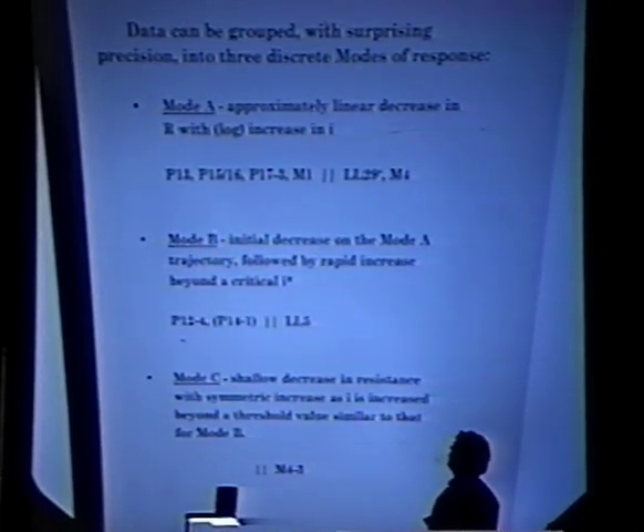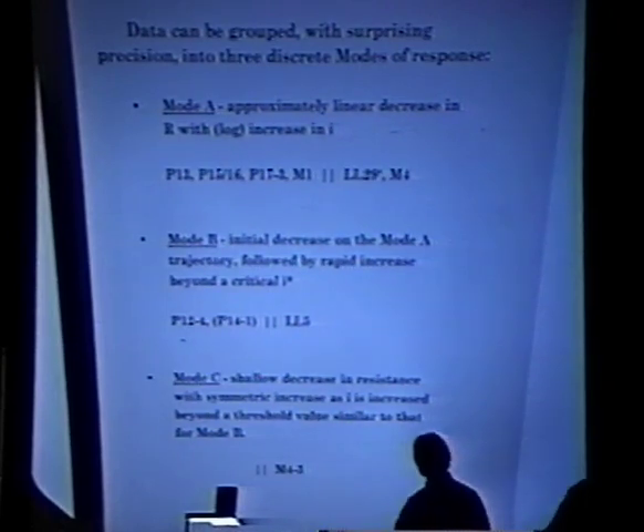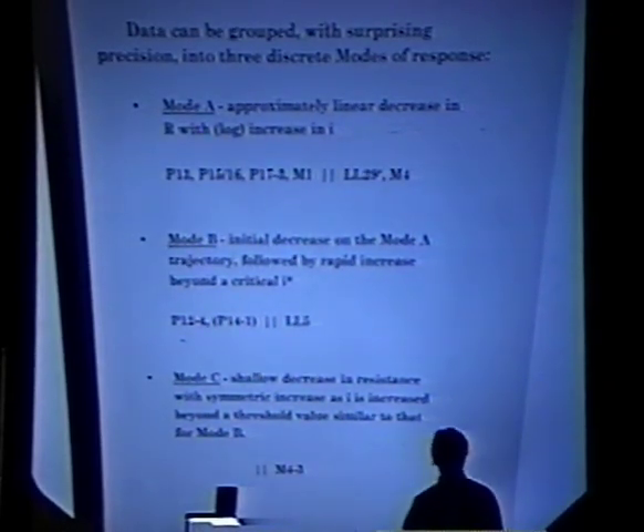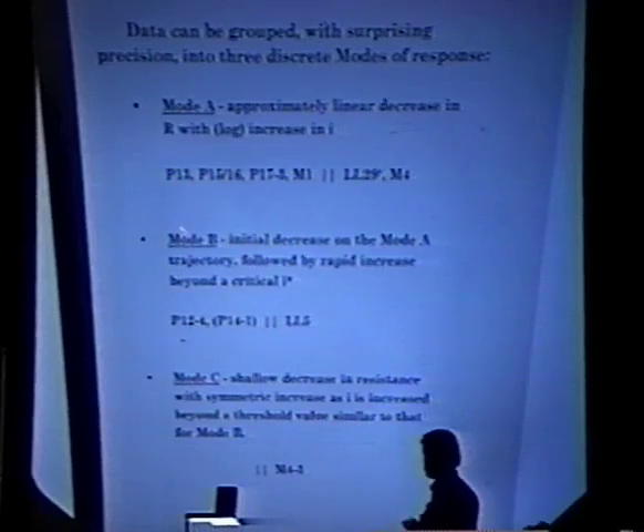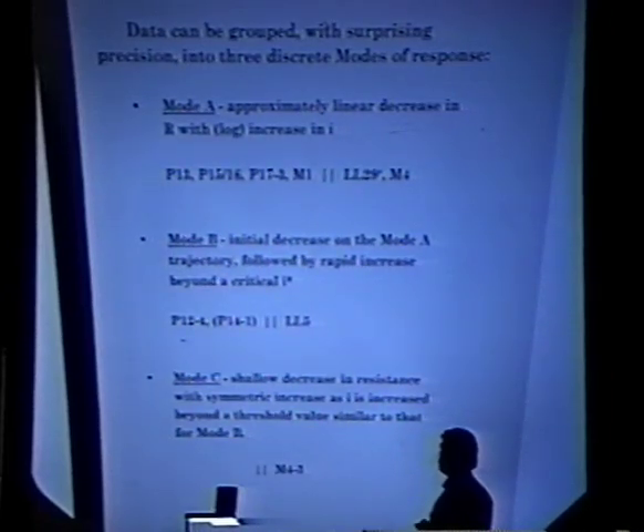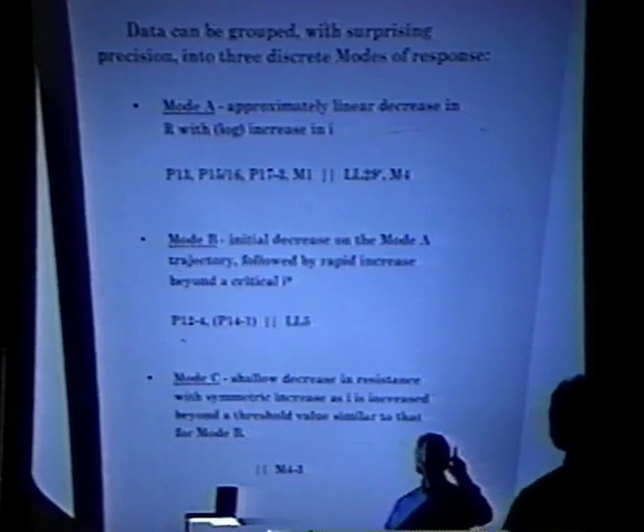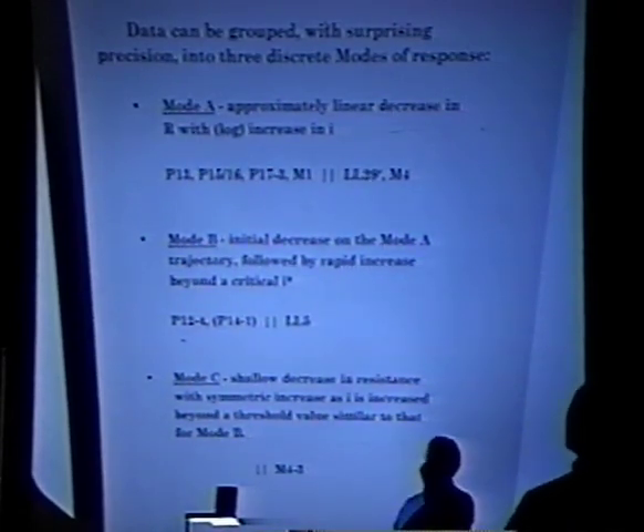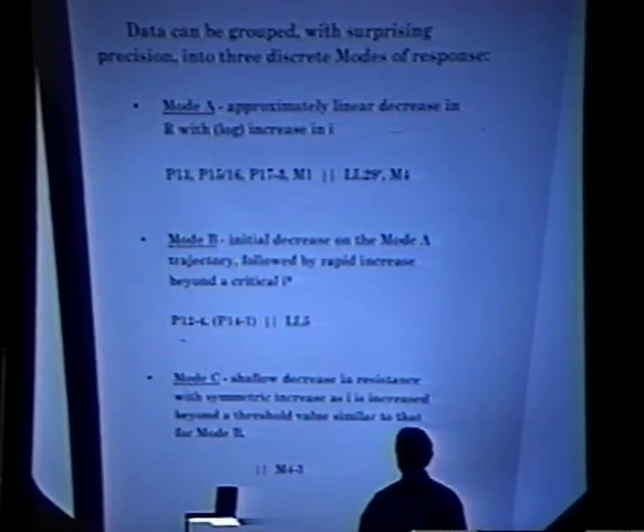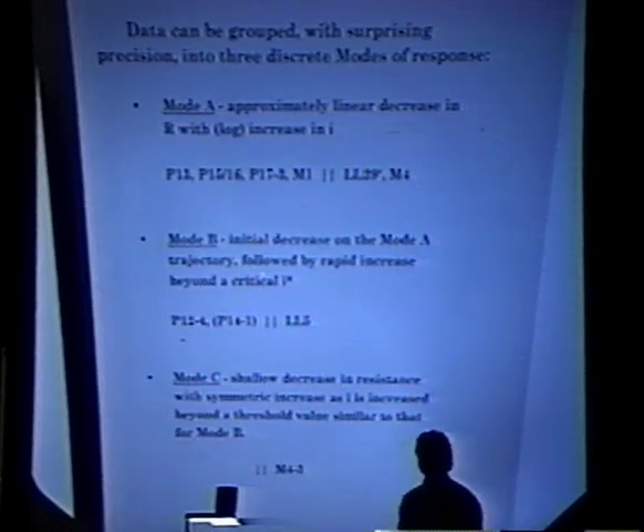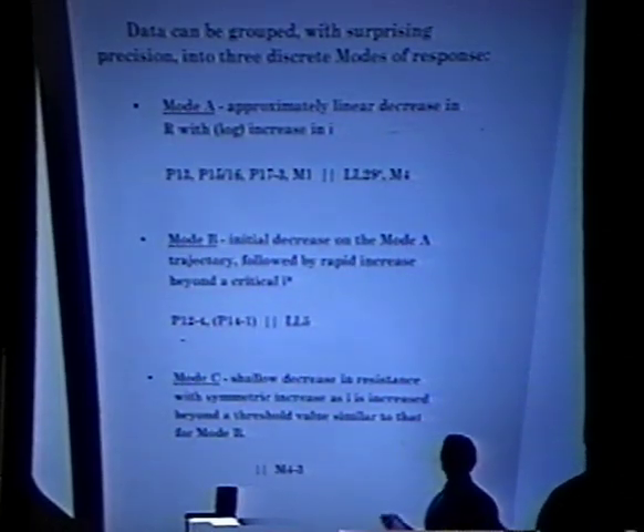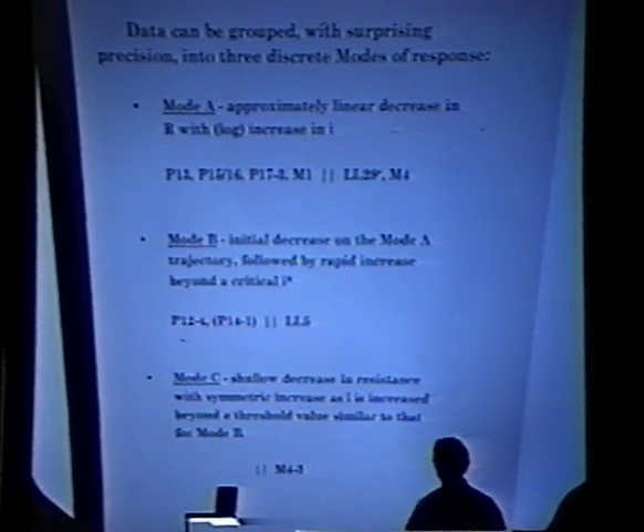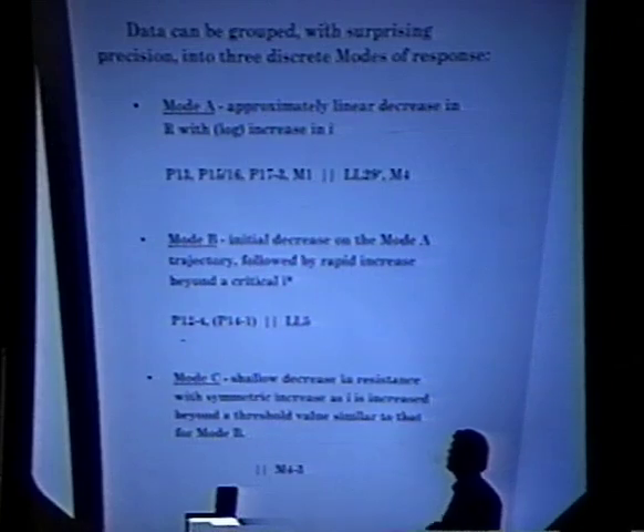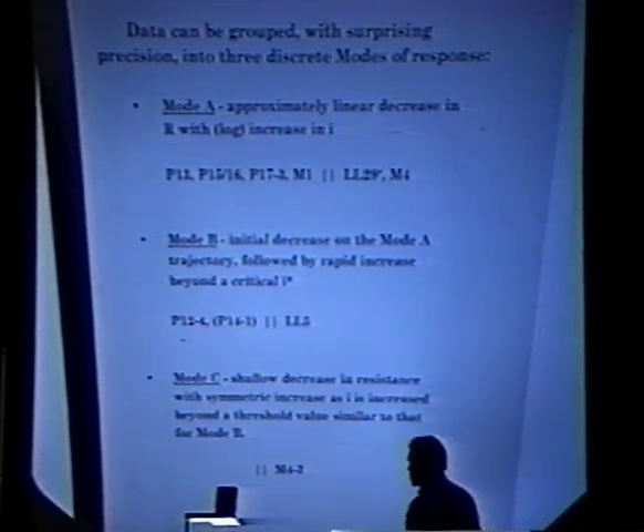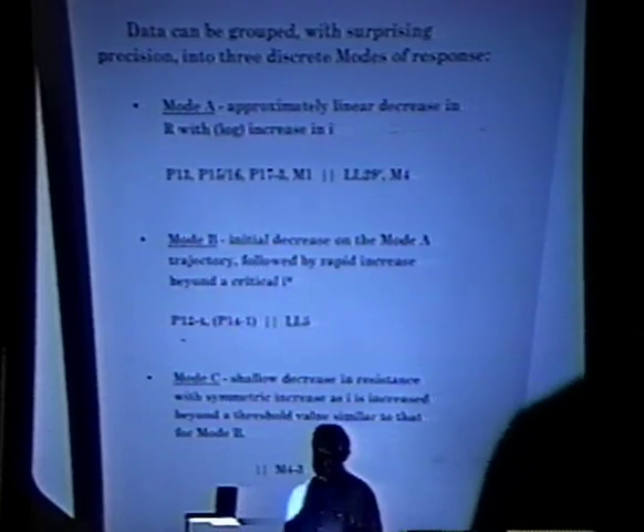Mode B initially follows the linear reduction in resistance with logarithmic increase in current density, but then it's followed by a rapid increase in resistance. The cathode attempts to load, and then for reasons which I want to discuss a little bit further, suddenly gives up. It can't get any more loaded. The resistance ratio can't decrease below a certain value. The cathode precipitously deloads.